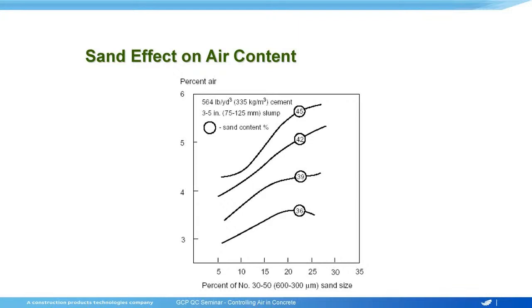When I make adjustments, when I'm testing, I make 1 cubic foot adjustments, which is about 100 pounds of sand. So if I think not enough sand is in the mix, I'll increase it 100 pounds, see if I move the needle at all. Making small changes, you may not see a change. So you make a big change, and then if it's too much sand for the look you're trying to get, you can back that down to 50 pounds and see if you get the same impact there. The amount of sand is definitely going to make a big impact on how easy or hard it is to get air and how much air you're going to get.